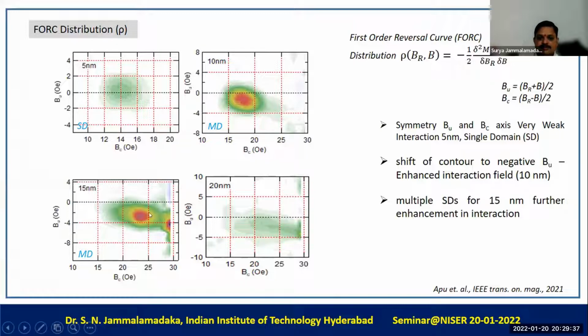For 15 nanometers, we see multiple domains. For 20 nanometers, we see the merging of the domains, and more and more magnetostatic interactions exist in the 20 nanometer film. Just by knowing the position of the contour diagrams, you can say whether it is in the single domain state or the multi-domain state. Since we don't have the superparamagnetic state and the vortex state in our system, we don't see that behavior. But if we had a system with the vortex state and the superparamagnetic state, you would also see corresponding changes in this contour diagram.